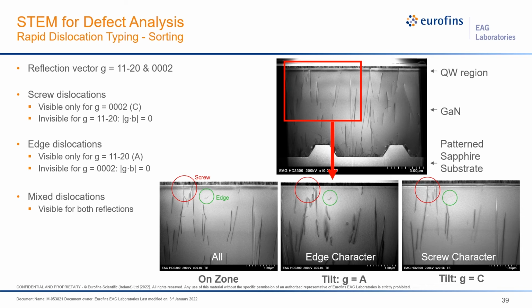And so it becomes important to then try to understand how these populations of screw and edge and mixed maybe vary between different samples, or in the case of defects that cause the issue, if we still have them present in the sample, we can then understand something more about how to potentially get rid of them by studying this. So in a lot of cases, it's not just defects that are maybe controlling the issue. It could also be layer compositions or even interface abruptness that becomes really important.